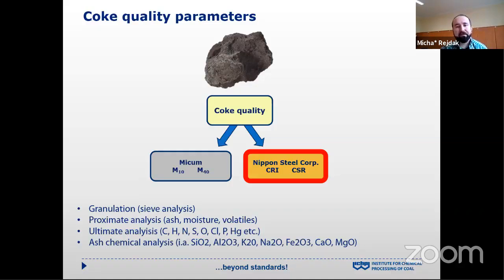So they can increase the reactivity of produced coke, which is not favored in aspect of blast furnace processes, because in general, the higher the reactivity of coke, the lower the coke strength after reaction.